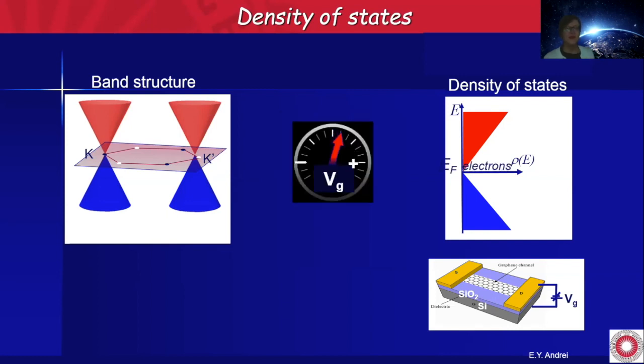And let's watch what happens. So I have positive gate voltage. My Fermi energy moves into the electron sector. Negative gate voltage moves my Fermi energy into the hole sector. Notice that I'm doing that without changing the chemistry. In three-dimensional materials, you'd have to change the constituents in order to do this. And you see that 1 volt of gate voltage buys me about 10 to the 11th carriers per centimeter squared, or it changes the Fermi energy by 80 millielectronvolts. So you see immediately we can change the properties just with a simple gate voltage.